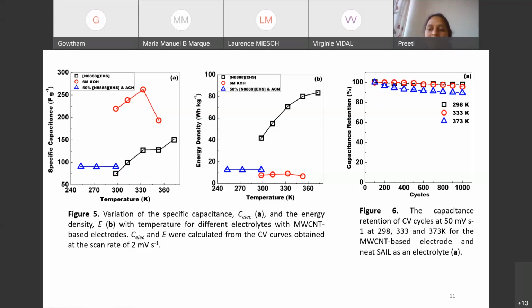So it might be difficult for the ions to go inside the pores of the electrode materials. But when we consider the aqueous electrolyte, the electrochemical potential window is very low. It's just 1 volt. And for the binary mixture of ionic liquid and acetonitrile, it's 2 volts.